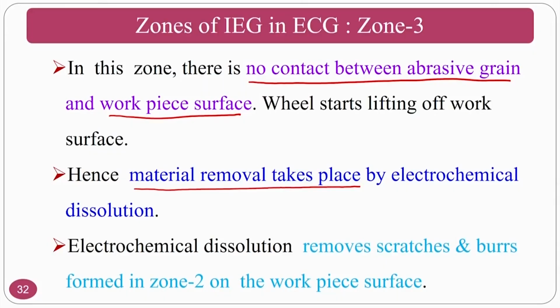Okay. So, that means that stage 1, stage 2, stage 3, or zone 1, zone 2, zone 3: zone 1 is purely electrochemical dissolution, zone 2 electrochemical dissolution plus abrasion, and zone 3 electrochemical dissolution. That means that in all 3 zones you have electrochemical dissolution, and at the same time you should note that if there is a burr generated by the abrasive action, that burr will be removed by electrochemical action.